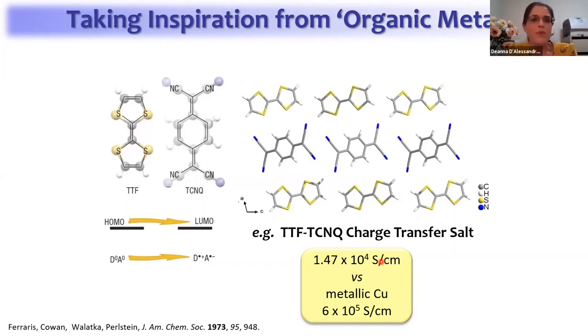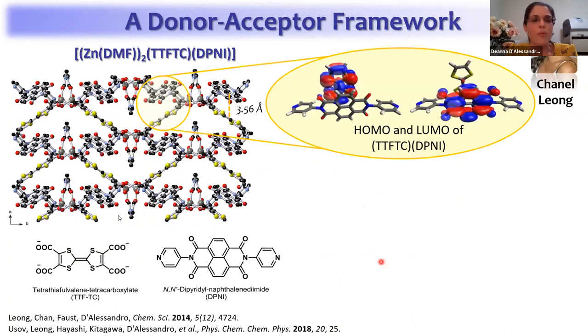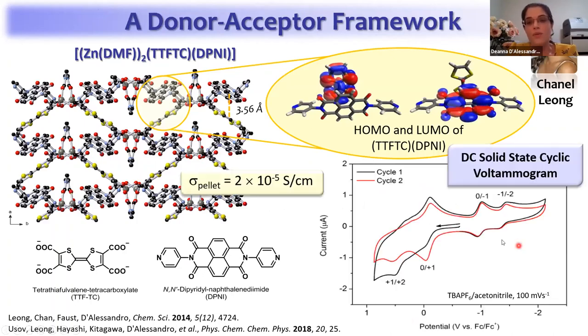So taking inspiration from that idea of incorporating both donors, in this case a TTF-inspired ligand, and acceptors, in this case a naphthalene diimide-inspired ligand, into metal organic frameworks, here's an example of a donor-acceptor framework. It actually has 5 accessible redox states, 2 as a result of the tetrathiafulvalene and 2 as a result of the naphthalene diimide. It is a semiconducting material.